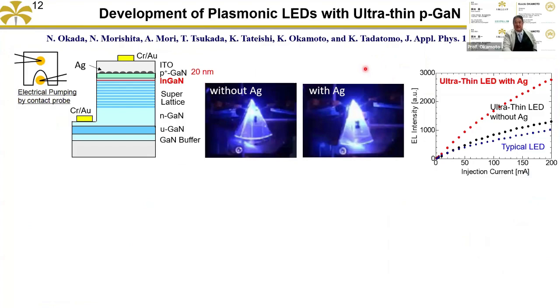Okay, then after I published the light enhancement in 2004, I said we could easily develop device applications, but the first device application came in the 2010s. It took more than 10 years because the device structure is a little difficult, since the light emitter must be very close to the metal surface. That's why the p-type layer thickness must be 10 nanometers or 20 nanometers. That's very difficult, to make the device structure and to keep the PN junction.